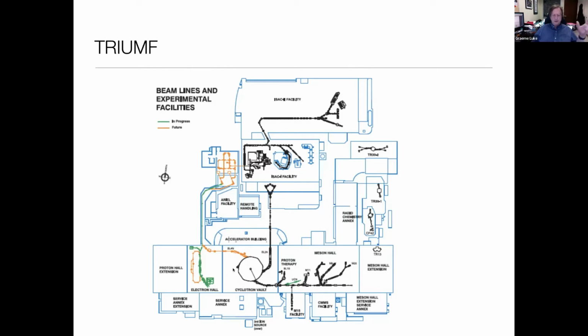So for these experiments, you need to have an accelerator. Here's an aerial schematic drawing of TRIUMF. The main accelerator is in the middle there. It's the world's largest proton, or actually a hydrogen minus accelerator. It's about 200 feet in diameter. Then the protons are extracted down this beam line here, where they hit a series of production targets, imaginatively called T1 and T2. And there we make muons, which are then fed into the secondary channels away from the target.